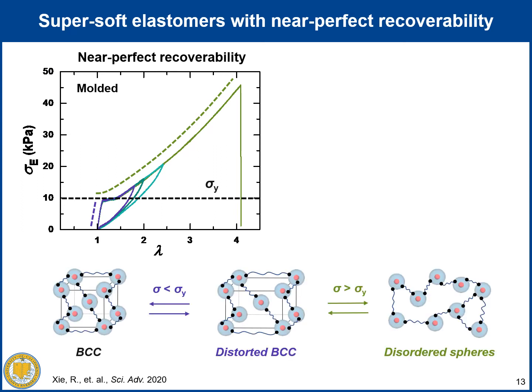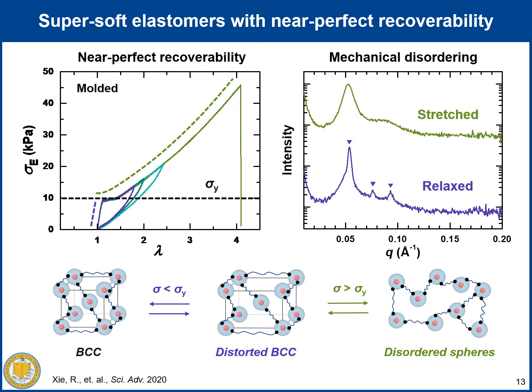Below the yield stress, we expect that the BCC lattice is only slightly distorted, while above the yield stress, the morphology of the stretched sample becomes disordered spheres. This mechanical disordering process is verified by the in situ tensile SAXS data, where you can see for the stretched sample, we lost the higher order reflection peaks.